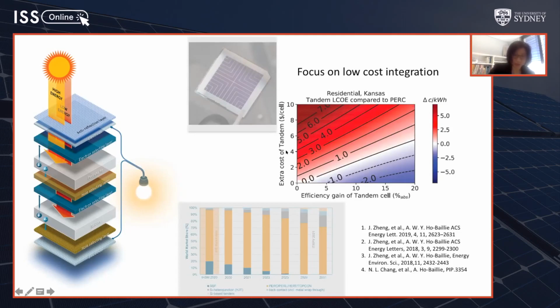So what this graph is saying, for example, is if the perovskite cell costs an extra $1.50 to make a tandem, then the efficiency of the cell needs to increase from 20% to 25% to break even. Now, this calculation assumes the perovskite cell will last as long as silicon. So this brings us to the holy grail of perovskite cells, which is durability.